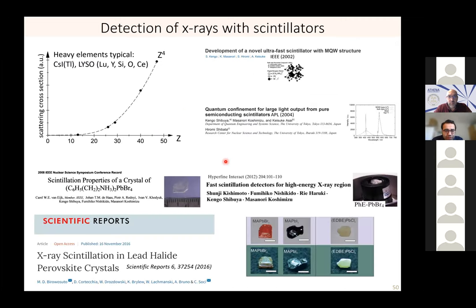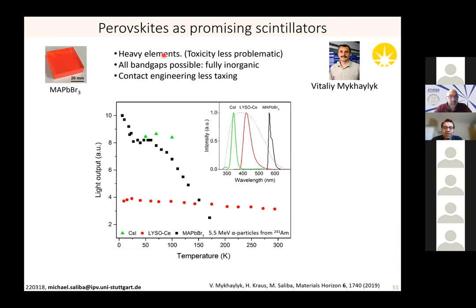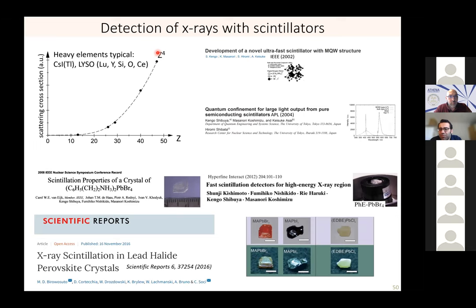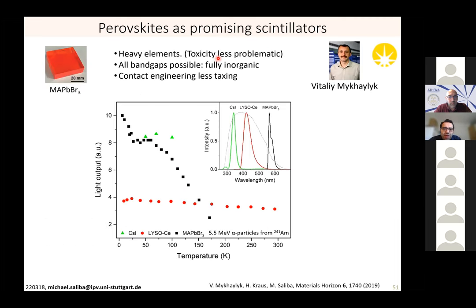And of course, perovskites are, I think, a particularly fascinating material because the heavy elements are less problematic for scintillators. So let me go back here. For example, even thallium doping is used, which is highly toxic and so on, but it's used because it has this high Z number. It's very deep down in the periodic system. All the band gaps are all of a sudden possible. If you have a gamma ray, it doesn't really care if the band gap is 1.5 or 3 electron volts. So this means we can go towards the inorganic perovskites. And then also the contact engineering is not such an important topic anymore, because the crystal itself is the device. So this, I think, is an interesting possibility.